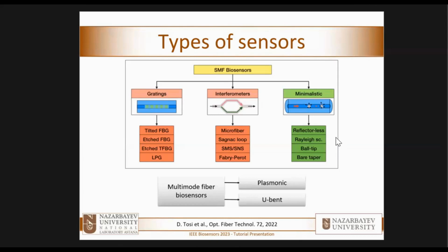If you take a multimode fiber and you do the deposition of a thin film using sputtering with appropriate thickness of the film, the sensor already has usually a plasmonic mode at visible wavelengths. And then you can detect that and tune it in order to match the wavelength that you want in your spectrometer, and that works. The problem of this method, however, is that they usually work not in reflection, but in transmission. So you need to place light source, sensor, detector. And that's not so practical.